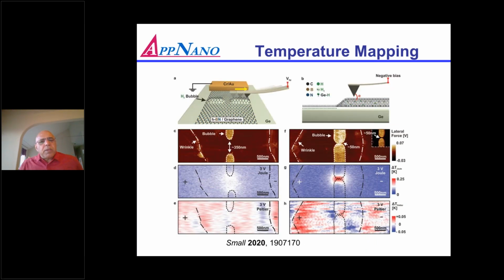Then this is a recent paper from a group in China, and what they were doing was making graphene with bubbles, and they designed these bubbles to measure the Joule heating and Peltier effect through the thermocouple probe. This is the same probe which we have developed that they're using, and as the two bubbles get closer, the temperature goes higher than when they are farther away. So this is the controlled effect of the graphene, and basically they are studying how heat dissipation will take place if graphene is used as a material in devices.